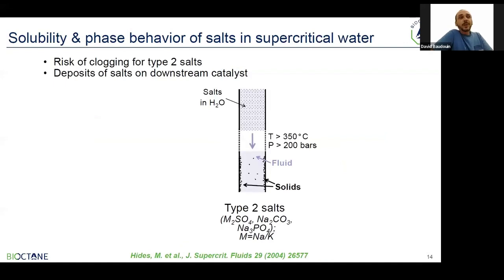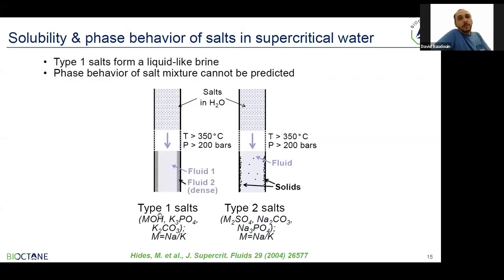So on one side, this can bring a lot of trouble, as these salts, if they precipitate on the walls of a continuous process, can clog the process, but they could also deposit on catalysts, which would also lead to trouble in a catalytic step of a process. This would be the case for some salts, not all of them, fortunately. Examples are sulfates, potassium or sodium sulfates, sodium carbonate, and sodium phosphate also. These salts precipitate and they are classified as type 2 salts. Next slide, please.